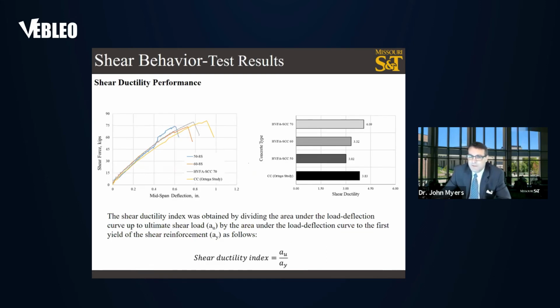Ductility was also a desirable structural property for the concrete member, so this was investigated. As you can see in the figure on the right, the bar graph shows the shear ductility calculated by the relationship of Δ at ultimate over Δ at yield, at apparent yield. And you can see that actually the high volume SCC 70 provided greater shear ductility than the conventional concrete with 100% Portland cement.